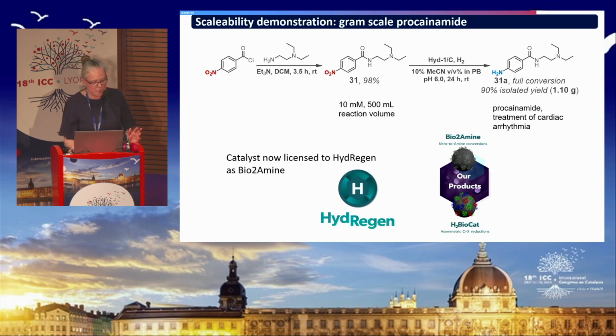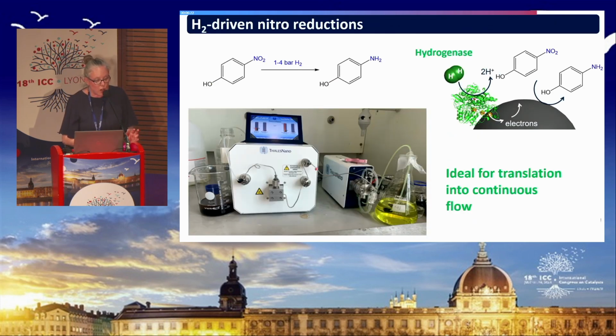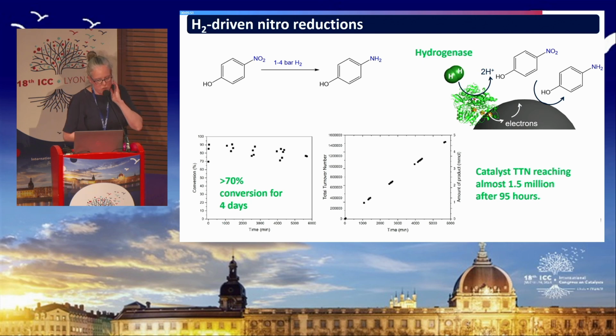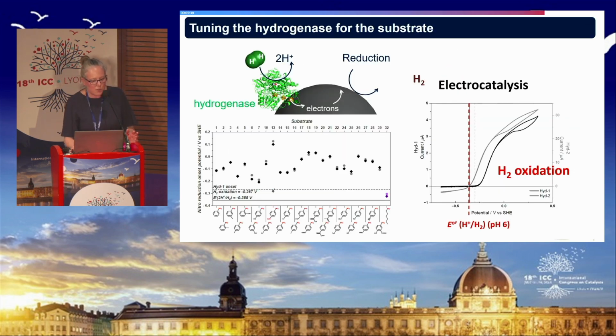fine chemical manufacturing. This is very readily translatable to flow because the enzyme's immobilized on a carbon support, and so this is a flow column incorporated into the commercial hydrogenation reactor, which produces hydrogen from electrolysis of water, and this is the hydrogenation of nitrophenol to generate the aminophenol, which is relevant to paracetamol synthesis in continuous flow. This was a very preliminary experiment without any optimization, and we straight away got over 70% conversion running for 4 days, giving us over 1.5 million turnovers for the hydrogenase during that time. So this is looking really promising.